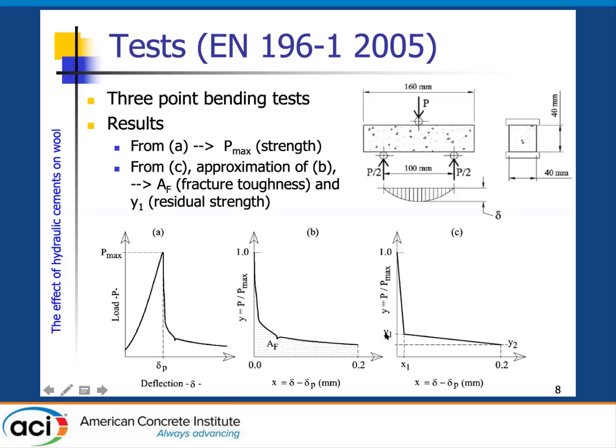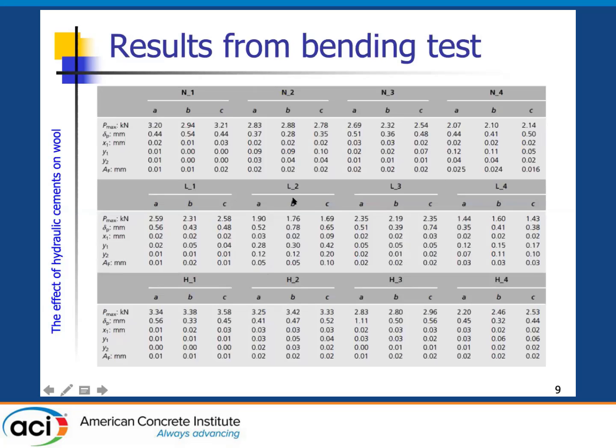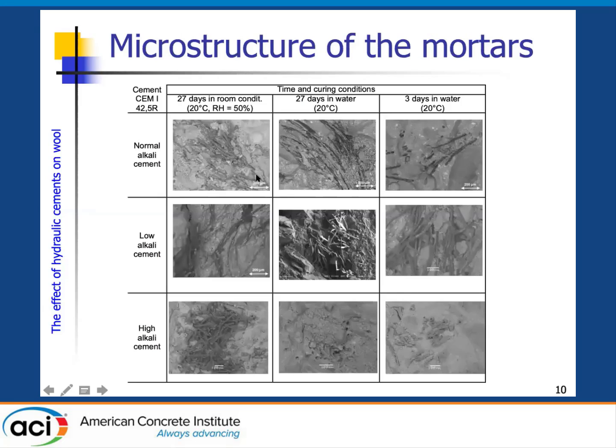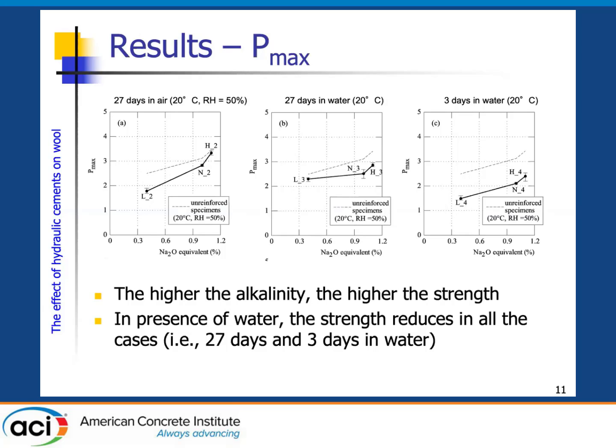So, this is an important parameter for evaluating the capability of the fiber to bridge the crack after the growth of the crack. So these are the results in terms of maximum load, deflection at peak, and in particular Y1 and AF, which is the area under the post-peak diagram. And we also observed the microstructures of the mortars after testing them in 3-point bending, and these are the pictures taken on the fracture surfaces. So let's investigate the results now.